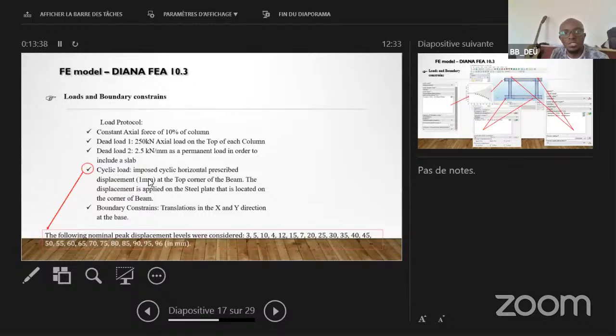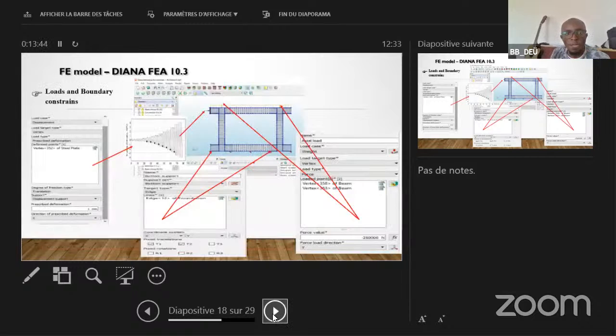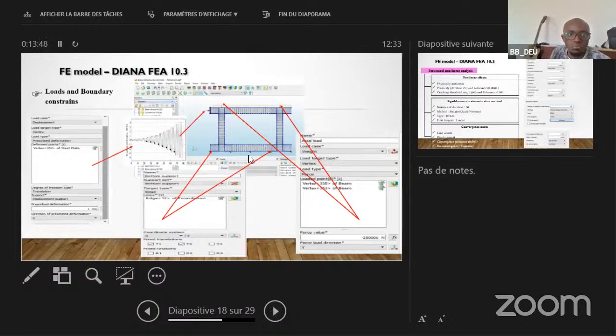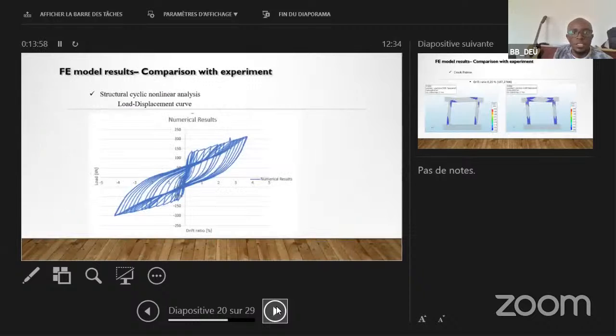And for cyclic loading, the nominal peak displacement was taken the same as the experimental. And you see how we define the constant load and place described. And as a result, we get the load displacement curve. And in this figure, we see there is pull and push. So push is stiffer than pull in our case. And also, there is good initial stiffness.